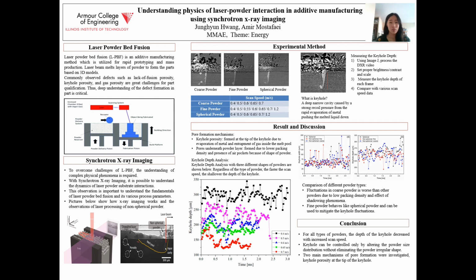With this process, we can observe the laser process such as generation of vapor cavity, melt pool, and porosity. In this experiment, we focused on measuring the depth of the keyhole. Keyhole is a deep, narrow cavity generated by a strong recoil pressure from the rapid evaporation of metal pushing the melted liquid down. ImageJ program was used to process the X-ray imaging video and to measure the keyhole depth.